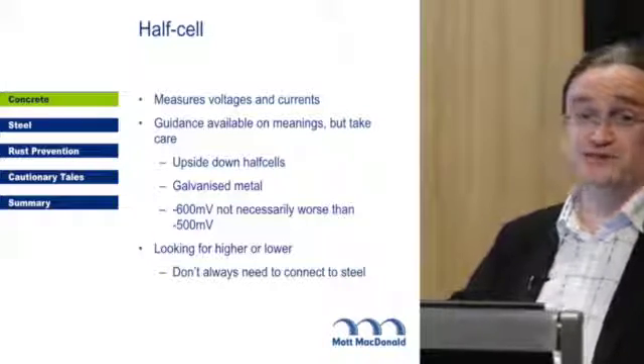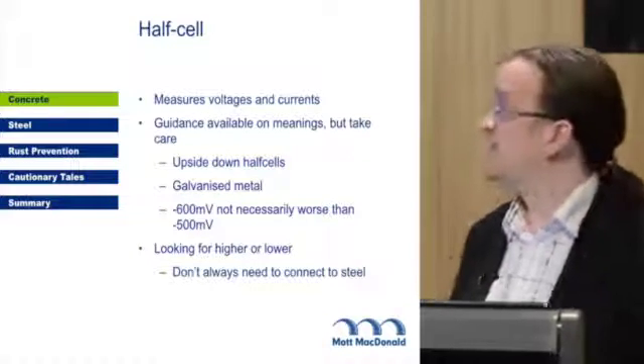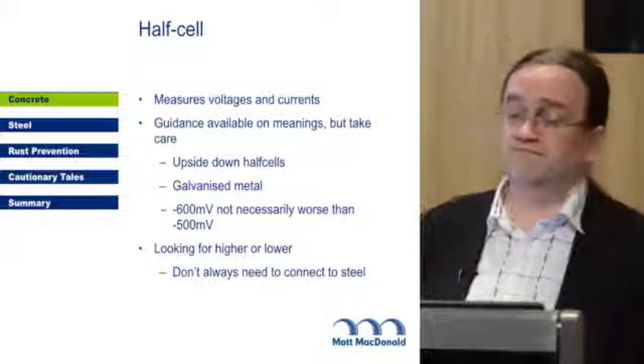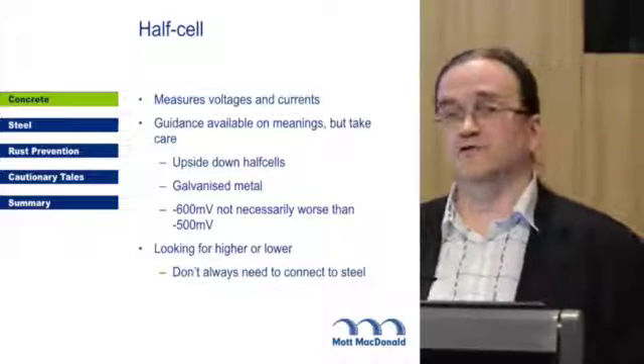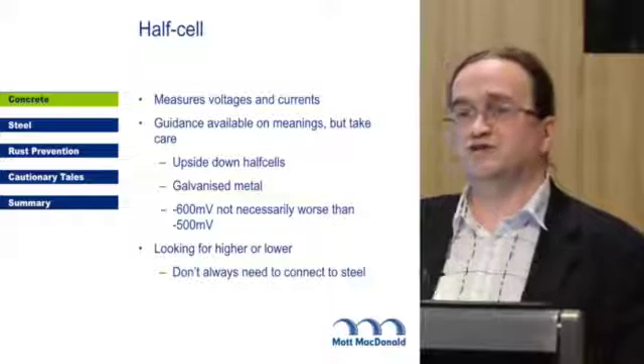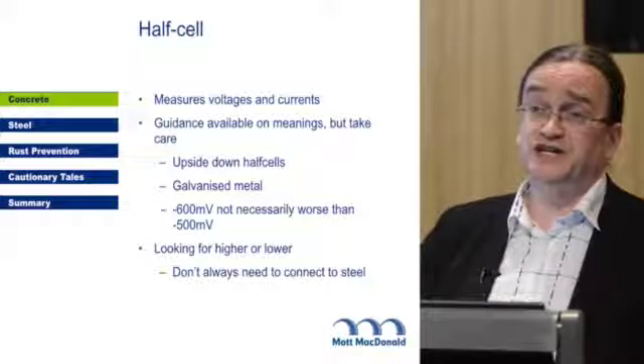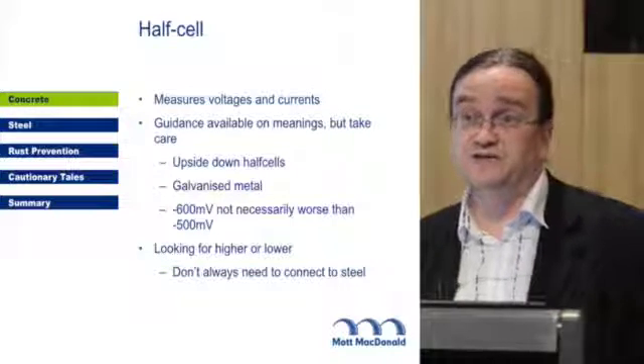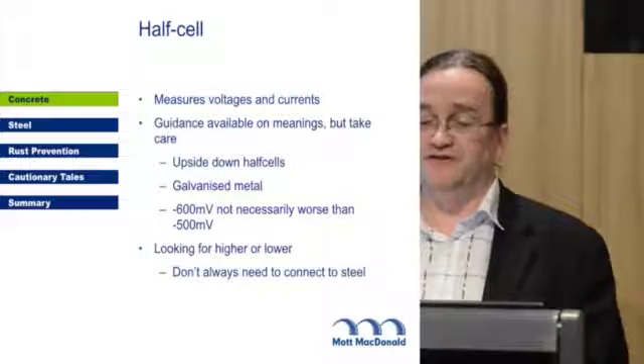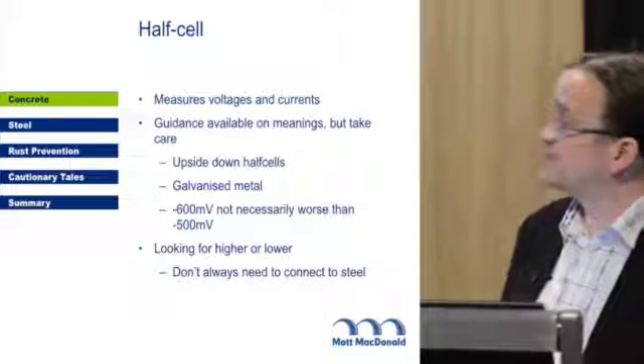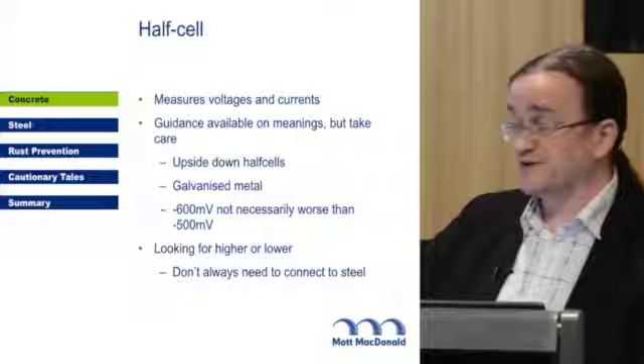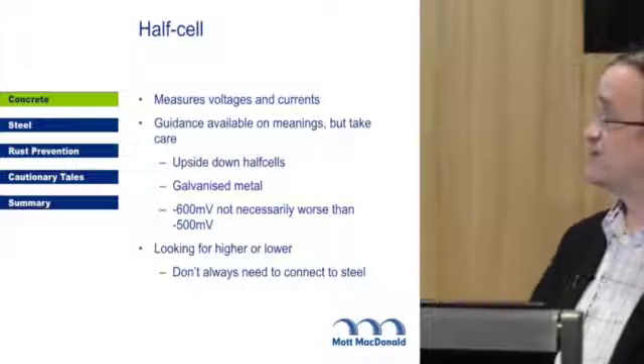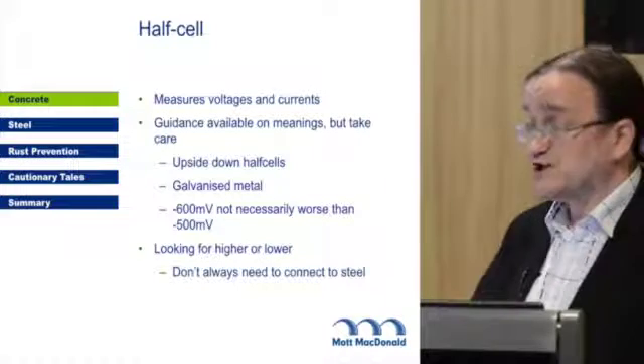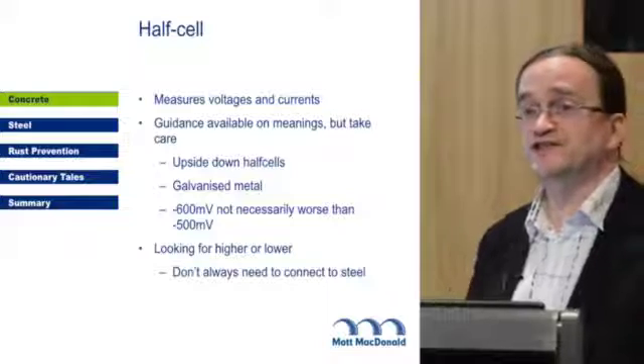It could just be there's a zinc post bolted into the concrete. Also, if you get down the bottom of a wall of an abutment, because there's not much oxygen kicking around on the buried stuff, the potential of the steel drops as you get down there. So it goes more negative anyway, even if it's not corroding. And what we're looking for is higher or lower. We're looking for Barry White and Jimmy Somerville. And Barry White's the one that's corroding. Because we're just looking for higher or lower, we don't always need to connect to the steel.